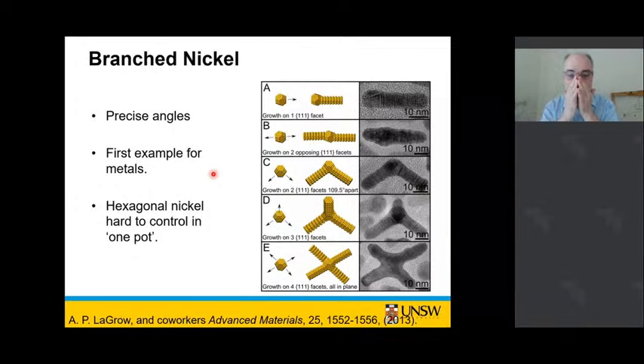So this was great. And this was the first example really with metals where you could use this kind of polymorphism structure using 2 different crystal structures to make a branch metal structure. So that was really good. But the problem is, as you can imagine, you're just putting your nickel precursor into one pot and decomposing it. It's quite hard to really control if you're going to get face-centered cubic nickel, hexagonal close-packed nickel, and also how to control that switch from one to the other.